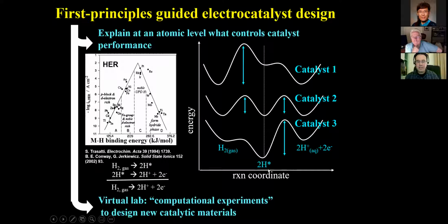And something that binds hydrogen very strongly might then have a high activation barrier, or a large energy input, or a slow rate to get the hydrogen off the surface and make the final product, protons and electrons. Something that binds hydrogen too weakly might be very slow to dissociate that hydrogen molecule, and have a high activation barrier for H2 activation in order to make hydrogen on the surface. And platinum, our optimal catalyst, gives us the optimal balance of not too fast, not too slow for either one of the two steps, and therefore the fastest overall rate of reaction.